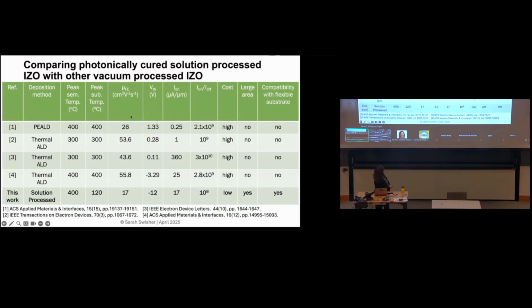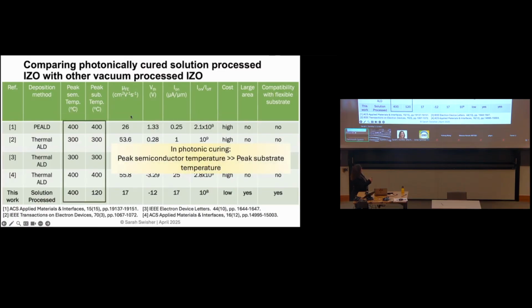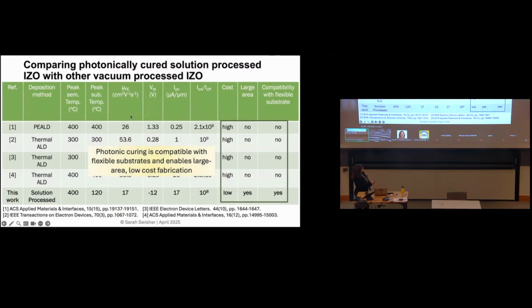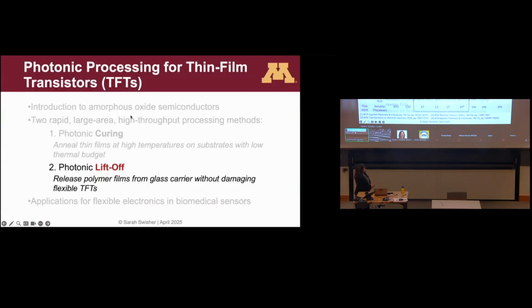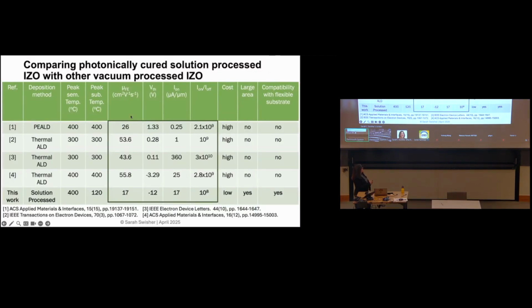I'm going to skip this comparison of all these different IGZO materials, except to highlight a couple of things. If you look at the peak semiconductor temperature and the peak substrate temperature, for all of these other processes, they're the same. Photonic curing allows us to process the semiconductor at 400 while the substrate stays at about 120 or lower. The other thing about photonic curing is that it's compatible with flexible substrates. It's compatible with large area deposition and fabrication as well, which is great. You can see that it's on par in terms of performance with these other devices. Not the best, certainly, but if you factor in this substrate temperature, this is really important for some applications such as flexible and also back end of line.